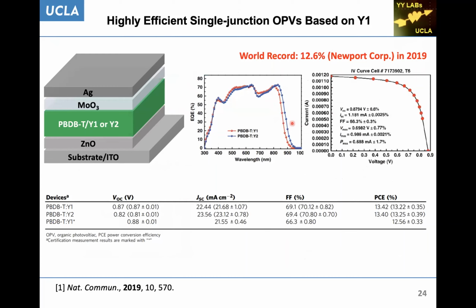And so this paper in Nature Communications in 2019. This one is 12.6%, Newport certified. This is our Y1 or Y2 molecule as an acceptor, and PBDBT as the donor material. We found that the absorption edge of a single junction device goes all the way to 900 nanometers, and you can see the EQE is 70%. It's not bad, but inorganic semiconductors can go to a much higher value.